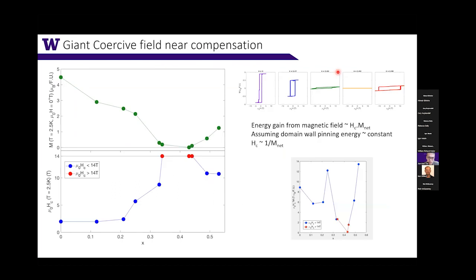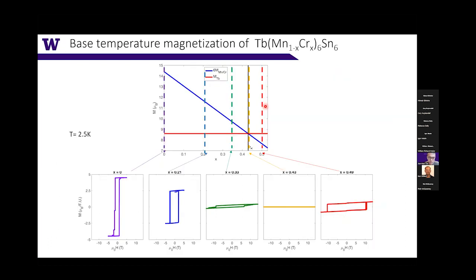Okay, so the immediate consequence of reducing this net magnetization, you can see, is the increase of the coercive field. So you can see that here in the parent compounds, the coercive field. Okay, maybe let's look at this.